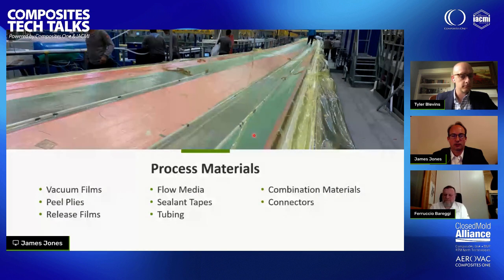So the green strips are the molded net flow media that's covering the solid skin portions, and that allows the resin to flow across the top and then down through the reinforcements. And then you can see the peel ply in this section where it's most likely covering a core. So in that area, they're using the grooves in the core as a flow media. So the resin flows through the grooves and then saturates the fairly lightweight skins over the core materials from there.